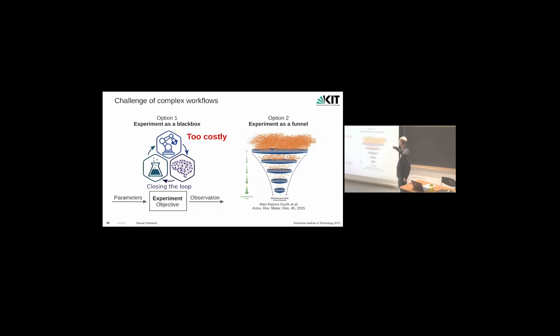So we start from, I don't know, 1 million molecules. Then we run DFT calculations on all of them and say, okay, we only select molecules that have a HOMO level of 4.2 electron volt and above because we have certain criteria. And then we can run, I don't know, synthesis experiments or something more complex maybe, to have another criteria and then narrow down further and further using predefined criteria to tell us what is a promising molecule.